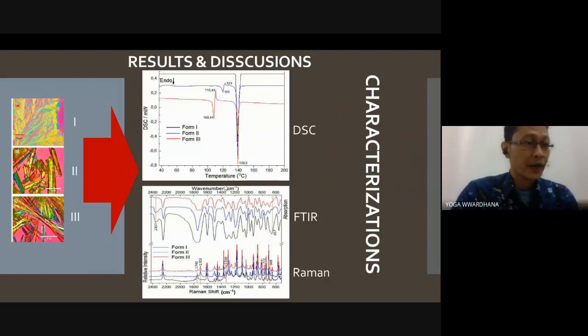Before that, we have to characterize the phase of the selected efavirenz forms under thermal analysis and vibrational spectroscopies. The thermogram shows that form 1 melts at 139.5 degrees Celsius, while form 2 at 120 degrees Celsius, and form 3 at 108.4 degrees Celsius. These thermograms tell us that form 2 and 3 are metastable and form 1 is the stable one.